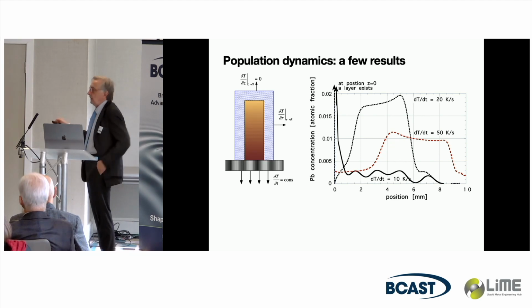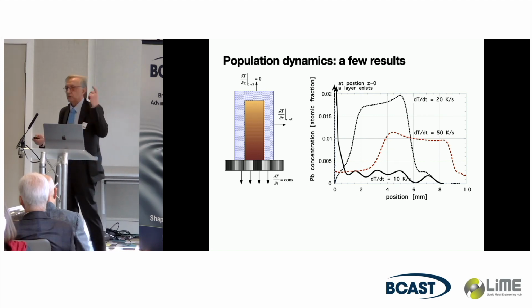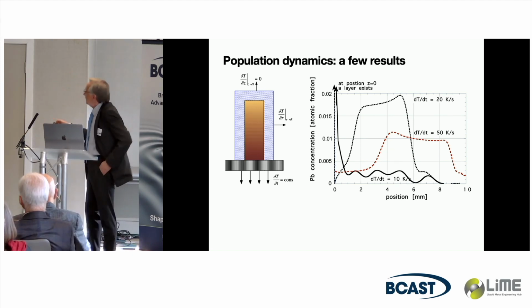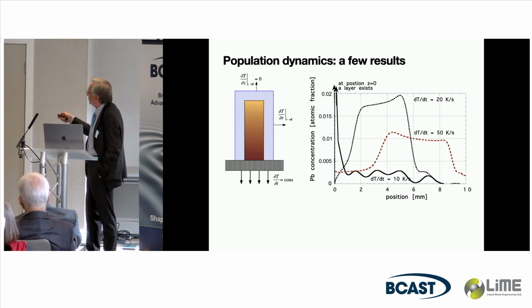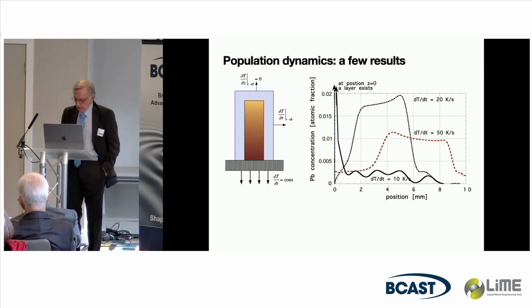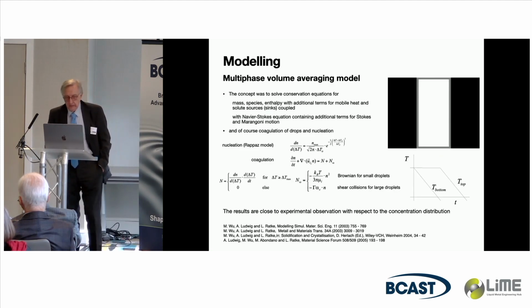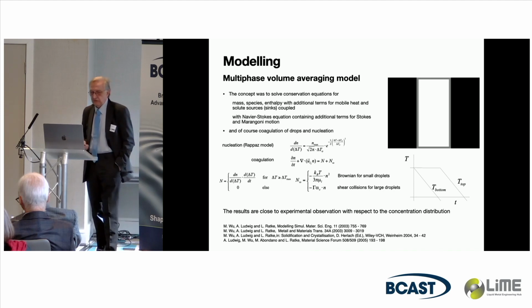At the bottom you have a layer, as you observed it in experiments. And then if you increase the cooling rate, Marangoni motion becomes more prominent because that's proportional to the cooling rate. And if you do it fast enough, you can indeed shift, even in gravity, a lot of droplets to the hot side of the sample. So, that's not the end of the story.